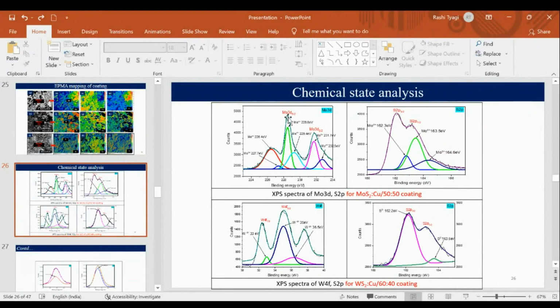We observed that there are Mo 3d peaks, or MoS2 peaks, that you can see. It means the Mo4+ compound is represented by Mo 3d, which shows the MoS2 compound. Basically, if you want to do chemical state analysis, you have to read the published literature to see at which peaks you can obtain MoS2 and hBN or any other element.